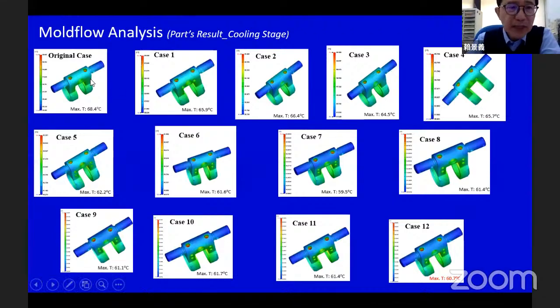For example, this result shows the surface temperature after the feeding stage, the distribution of the surface temperature from the minimum temperature to the highest one. And here we show the highest temperature. For the original, the surface temperature is 68.4. We want to reduce the highest temperature. For different designs, as you can see, the temperature decreases slightly, but is still not satisfying until we reach this one. The highest temperature is the minimum one.